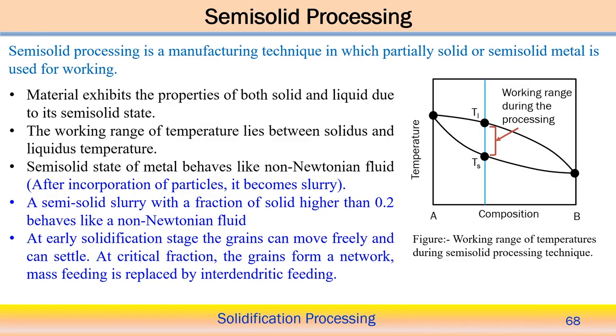So we understand that in the semi-solid processing technique, the working temperature is between the solidus and liquidus temperature for a particular material and a particular composition. We follow the manufacturing or processing of the semi-solid material in such a way that it creates a critical value of the solidified fraction in the mushy zone, and then we apply some mechanical shearing to this partially solidified component over the liquid, such that we can represent the complete component in the form of a slurry.